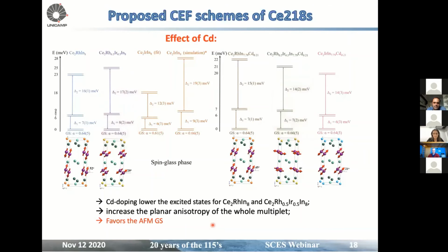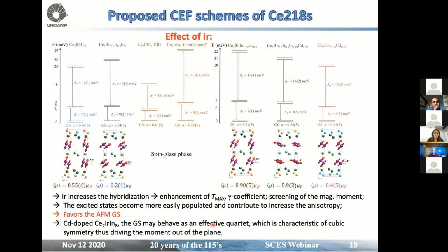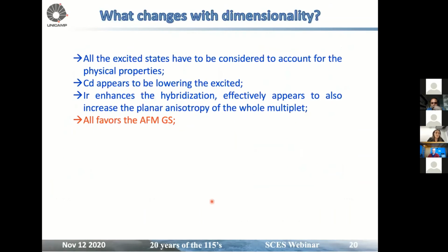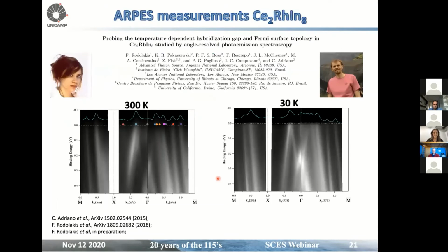And also the effects of iridium. So iridium increased hybridization, as we could see from Tmax and the gamma coefficient. Also, we have the screening of the magnetic moment. So excited states become more easily populated, which in fact could contribute to also increasing the anisotropy, and in the end it favors antiferromagnetic ground states. So what then changed with dimensionality? So first, all the excited states have to be considered to account for physical properties. Cadmium appears to lower the excited levels. Iridium enhances the hybridization. And all of this favors, in the 218 scenario, an antiferromagnetic ground state. So now I jump to ARPES measurements on Ce2RhIn8, a little bit late on time.